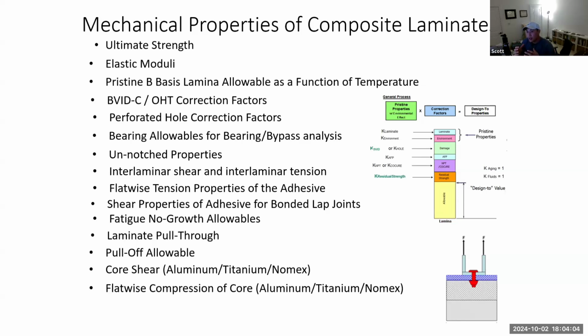And there can sometimes be a high out-of-plane load with respect to the skin, and the out-of-plane load will tug on the fastener head and pull through the laminate. It's a critical failure mode. Pull-off allowable. So in this example here, you have a fitting with a fastener with a face sheet that's bonded to the core. And if you have a high out-of-plane load, it's going to impose an out-of-plane load that's going to be imparted through the adhesive. So we need to know what the tension pull-off capability of the adhesive is.